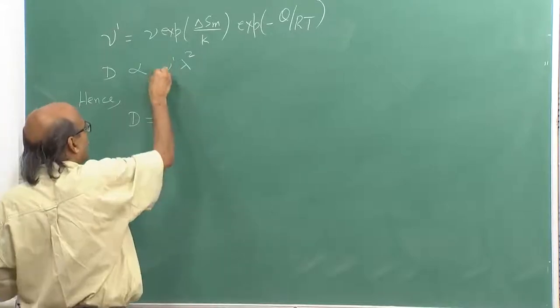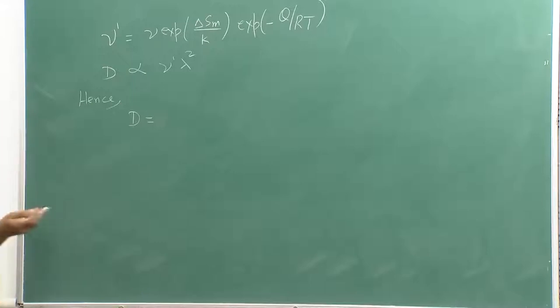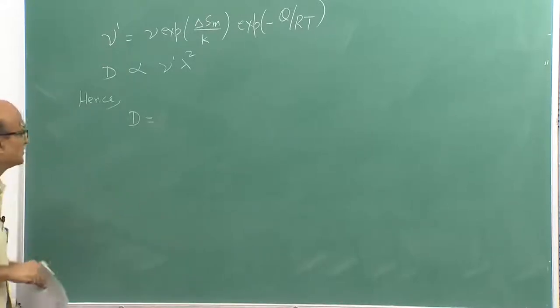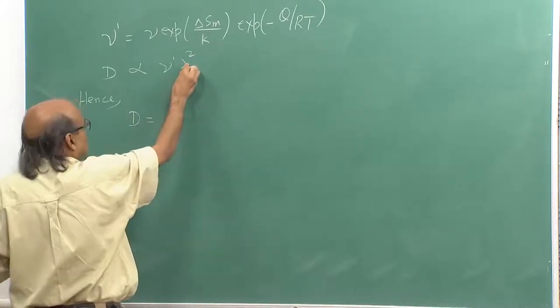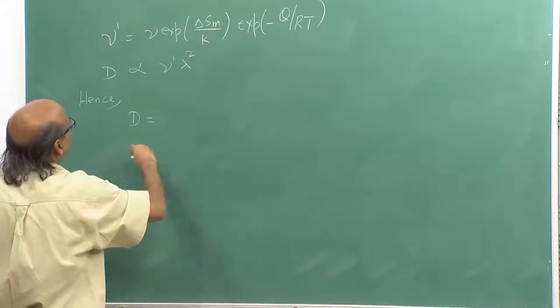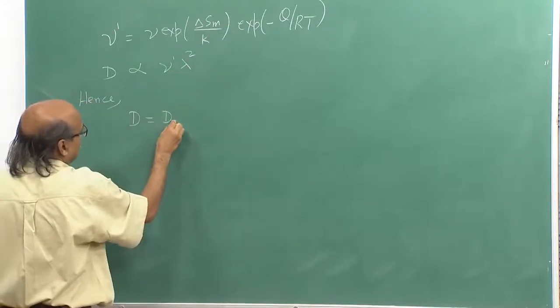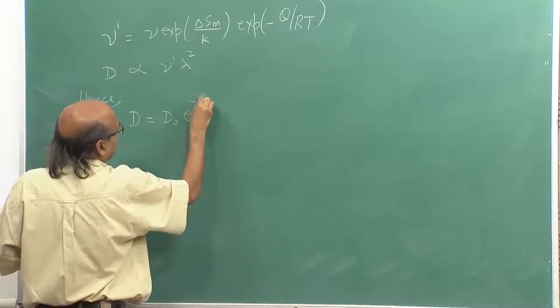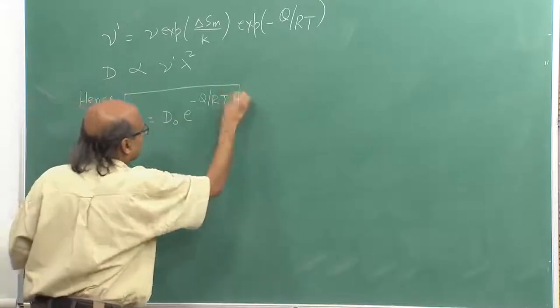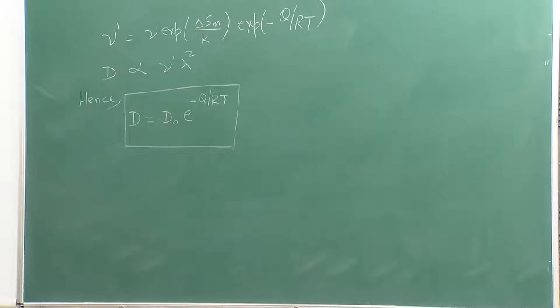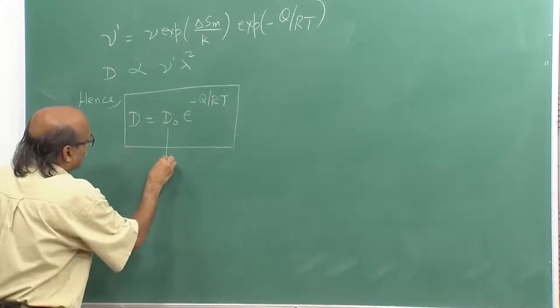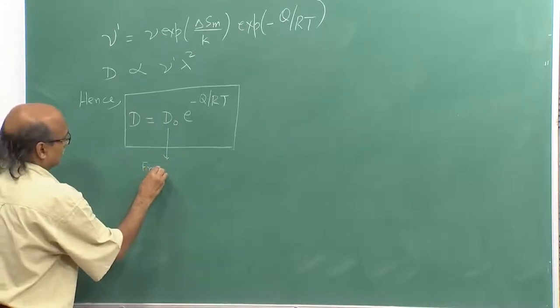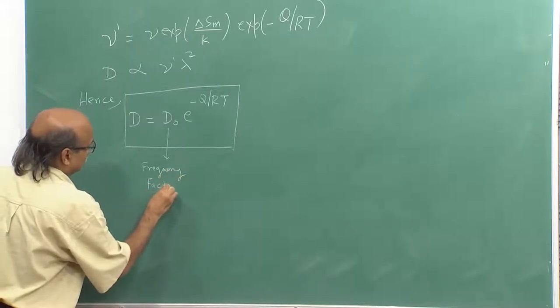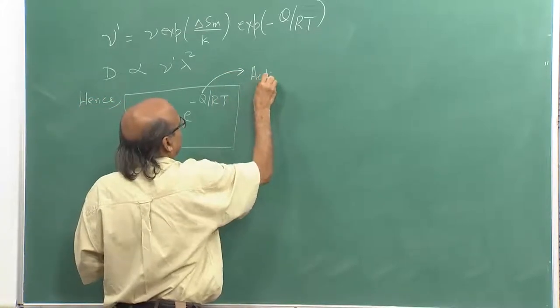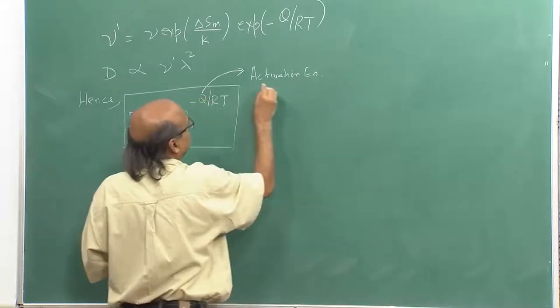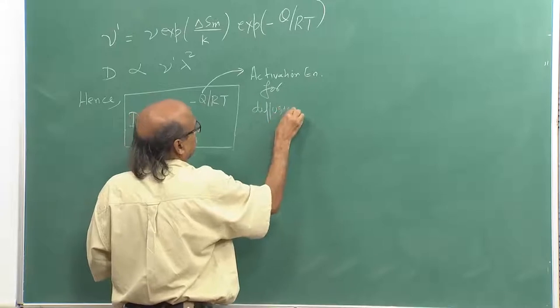I can lump in some constant of proportionality here, which is going to be a function of the geometric factors, like what kind of crystal structure and in what direction you are considering diffusion, and in addition to that, the jump distance and nu prime. So, D could be written as all the temperature independent terms lumped into a parameter D0, e to the power minus Q by RT. So, this represents the final expression for the diffusion coefficient as a function of temperature. Here D0 is also termed the frequency factor, and Q is called the activation energy for diffusion.